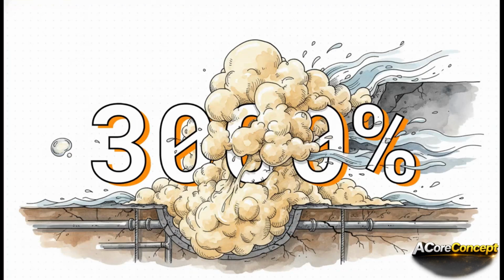Section 5, selecting optimal resin density. When you factor in the expansion component, the cost efficiency of polyurethane becomes honestly staggering. Get this, some emergency PU resins, the ones specifically designed to halt catastrophic water inflow, have a foaming expansion capacity of up to 3,000%. Yeah, 3,000. That means a tiny amount of liquid resin transforms into a massive void-filling structural plug almost instantly.